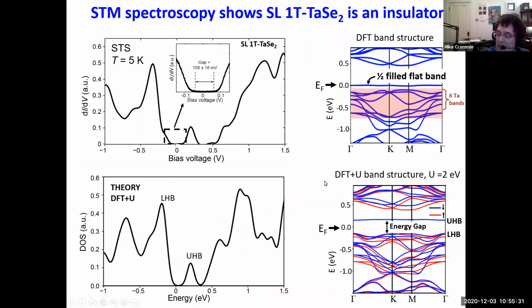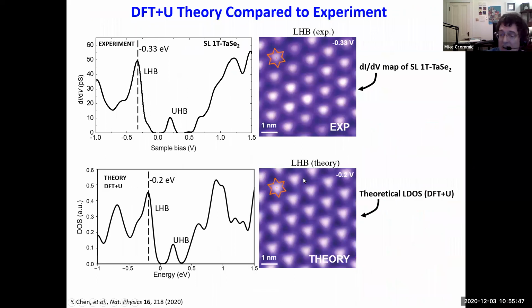And when you plot the density of states from this DFT plus U calculation, you see that it actually looks pretty reasonably close to what we see experimentally. Maybe even better than you would expect. So you get this lower Hubbard band here, this peak, and you have the upper Hubbard band here. And if we actually look at the wave function from the DFT plus U, it also matches the experiment pretty good in the lower Hubbard band.